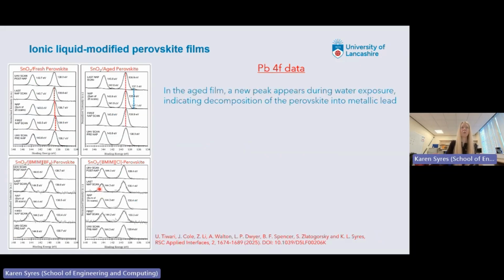And then this is just some data from the lead, because I mentioned that you can actually get degradation all the way to metallic lead. And so for our aged film, when we exposed it to water, during the actual exposure to water process, we saw this extra peak coming up. And this is the decomposition of the perovskite into metallic lead, which is the final stage of decomposition. So this is now very heavily decomposed at this point.